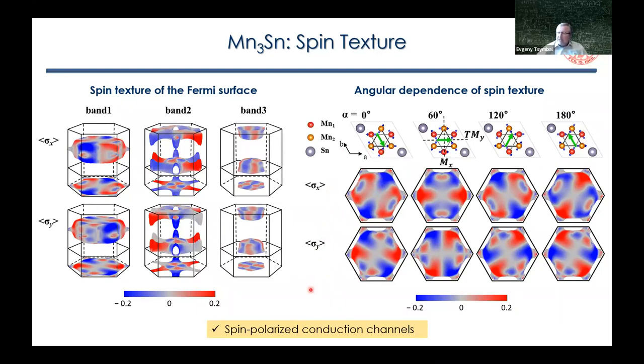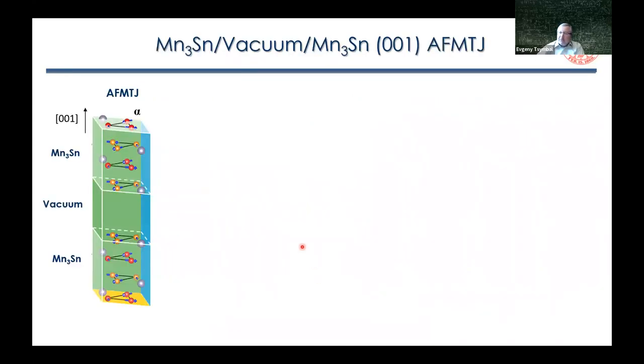So we should expect from this simple consideration that there should be a sizable tunneling magnetoresistance effect driven by this matching or mismatching of the spin at the Fermi surfaces. So now let's show the results of calculations. In these calculations, for simplicity, we assume that there are two magnetic Mn3Sn electrodes separated by a vacuum barrier. This is just for simplicity, because all the calculations and all the ideas are based on the band structure of the bulk antiferromagnet.